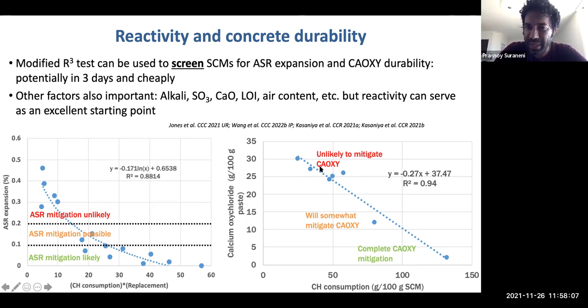So similarly, for calcium oxychloride damage, we can separate out materials into these materials which are really very unlikely to mitigate it because they have very low calcium hydroxide consumption and lead to very high calcium oxychloride contents in paste or concrete. Materials here which are somewhere in between, where they may be able to mitigate calcium oxychloride damage, but other factors might be more important. And highly reactive materials which will likely completely mitigate calcium oxychloride damage.